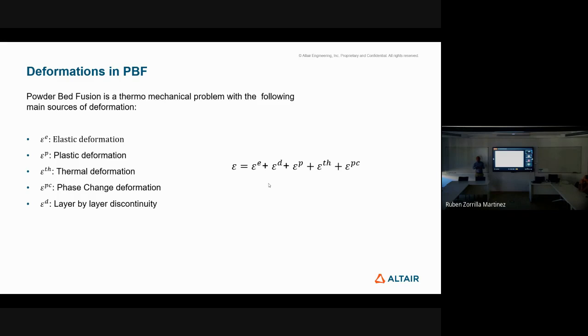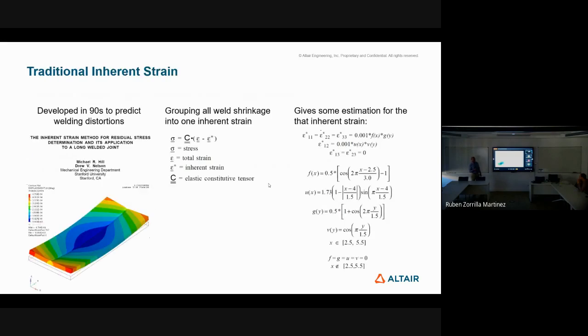So in each layer that you put over the other one, there is a discontinuity. They are not continuous when you deposit. This is something important to consider. And your total strain is all of them together. That said, people have been using inherent strain in welding many years ago, in the 90s. The idea was that you take your normal strain and say your strain is a function of your mechanical strain and the strain that is induced by the shrinkage.